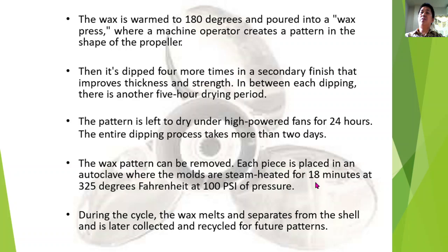Each piece is placed in an autoclave where the molds are steam heated for 18 minutes at 325 degrees Fahrenheit at 100 psi of pressure. During the cycle, the wax melts and separates from the shell and is later collected and recycled for future patterns.